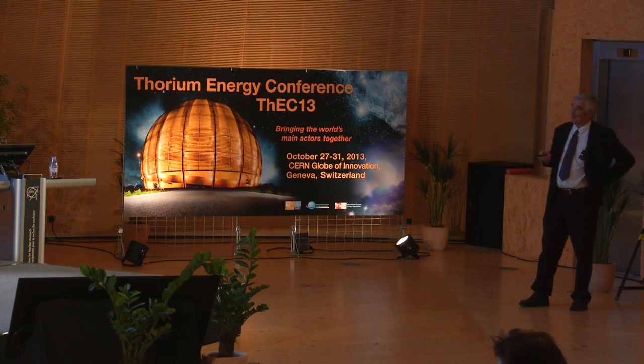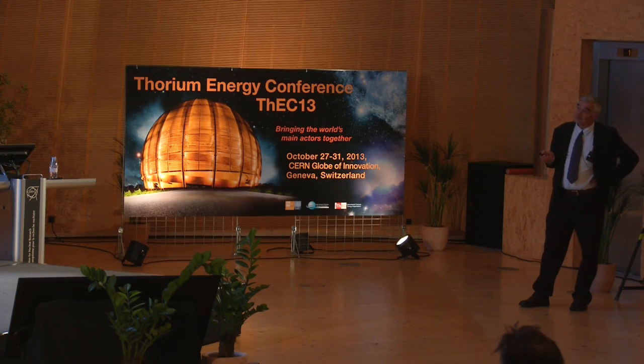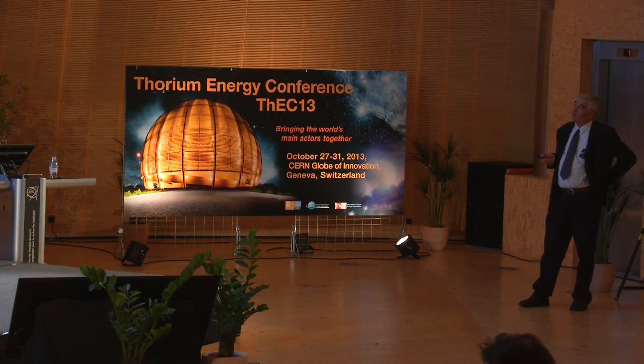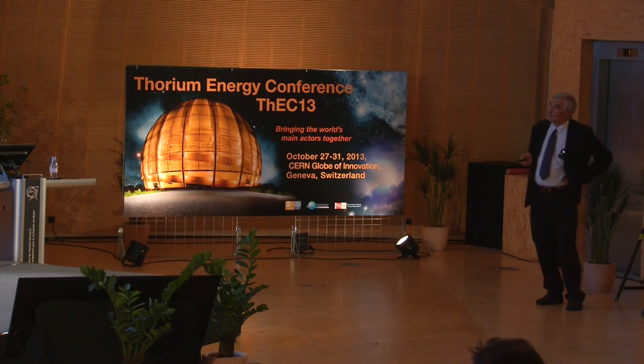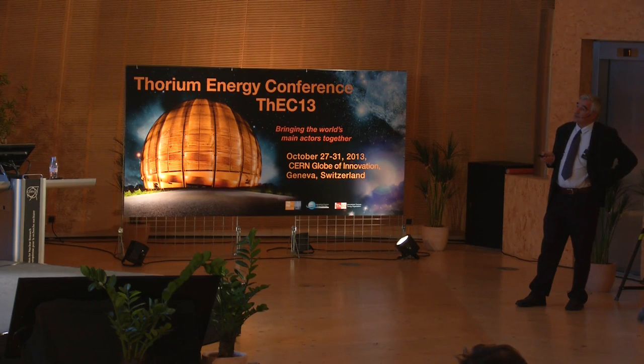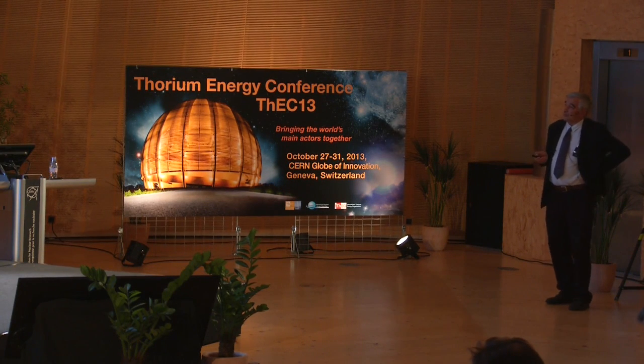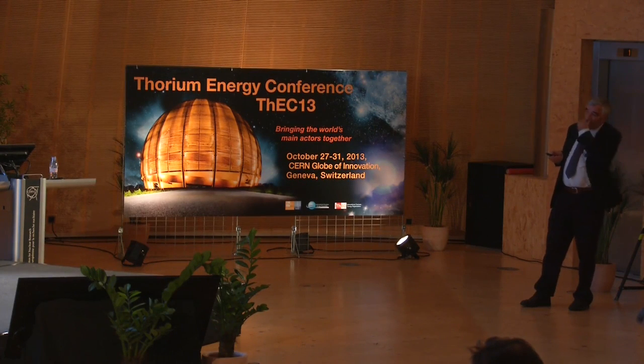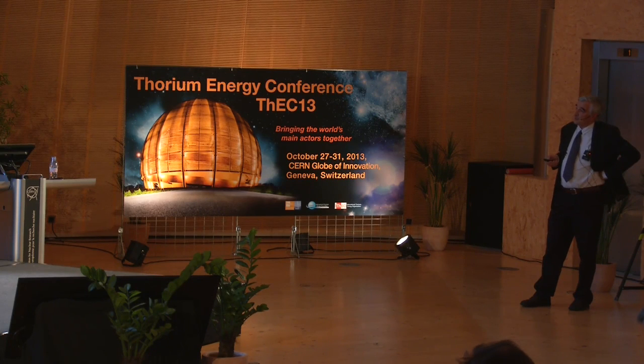No transportation, but okay, irradiation. In order to analyze the samples, what we need is effectively to have a good mapping of the irradiation parameters, of course, such as irradiation dose, helium and hydrogen production, proton and neutron fluence, irradiation temperature, and temperature itself. We made some calculations of the proton fluence distribution, and there were some measurements also. The proton fluence distribution was established from the measured data, and what we have observed is the maximum proton fluence of the MEGAPIE target at this value, 1.93 10 to the power 25 protons per square meter.